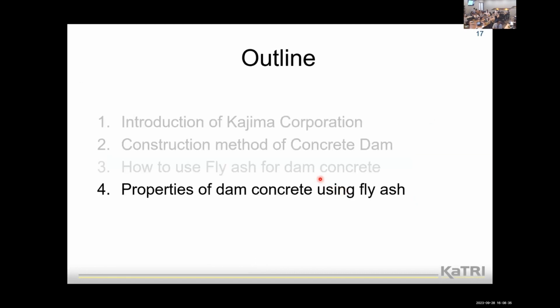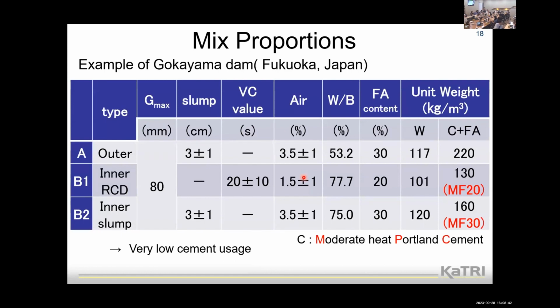Okay. Lastly, we explain the properties of dam concrete using fly ash. This slide shows the mixed proportion of our dam site, the example of Gokayama Dam, which was built in Fukuoka in Japan. Mix A is the outer concrete, so the water binder ratio is 53.2 and the fly ash content is 30%. As cement, moderate heat Portland cement is used. We call this type of cement MF20 or MF30. For the outer part, durable concrete is needed, so the unit weight of binder is 220.